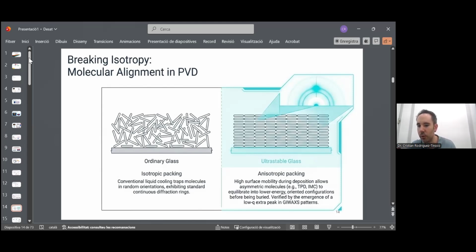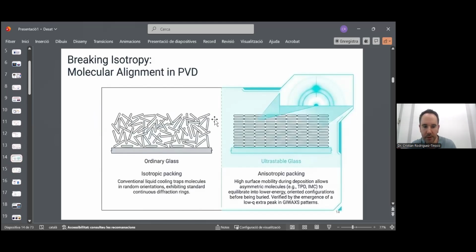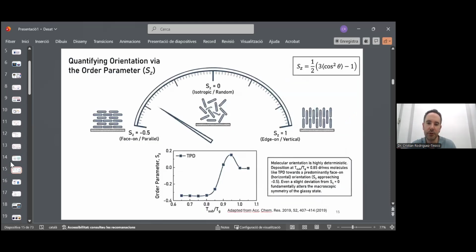And this has been verified, for example, by X-ray diffraction. I have some plots afterwards, which you will see. So this is the idea. The degree of orientation can be parameterized with this parameter S, okay, which is just a way of measuring the angle, the degree of orientation with respect to the substrate. So if this parameter S is equal to 1, it would mean that all the molecules are perfectly aligned in this direction, perpendicular to the substrate. On the other hand, if this parameter is minus 0.5, it would mean a perfect orientation parallel to the substrate, okay? And 0 would be completely isotropic. And this is what we have experimentally.